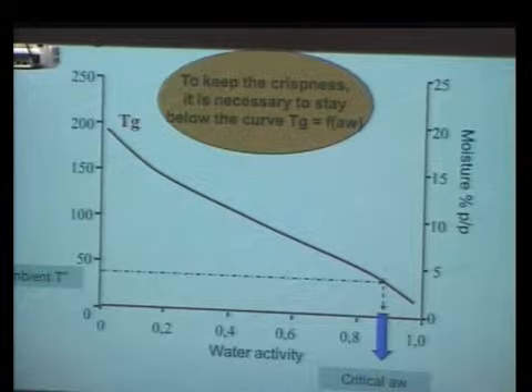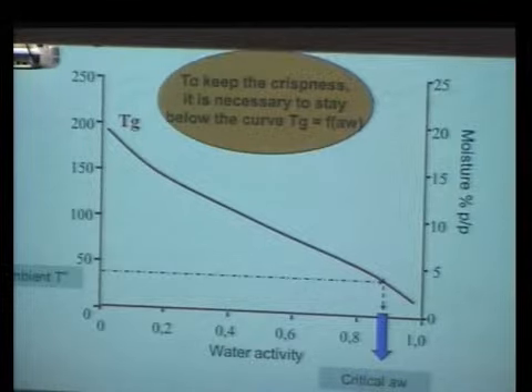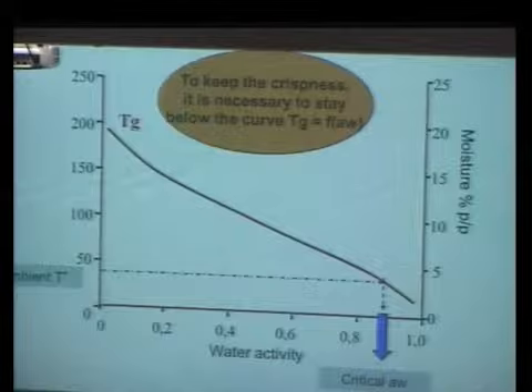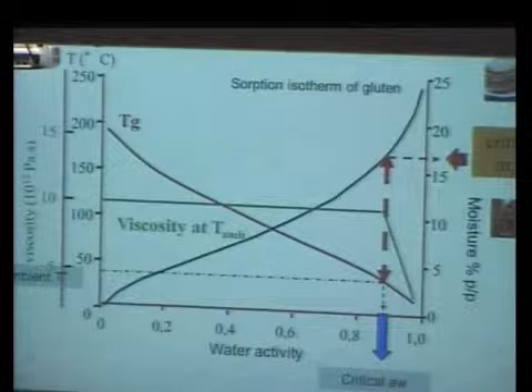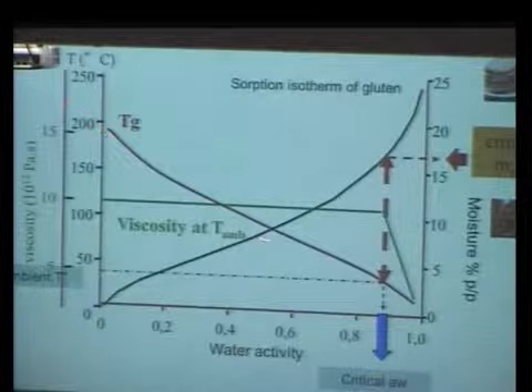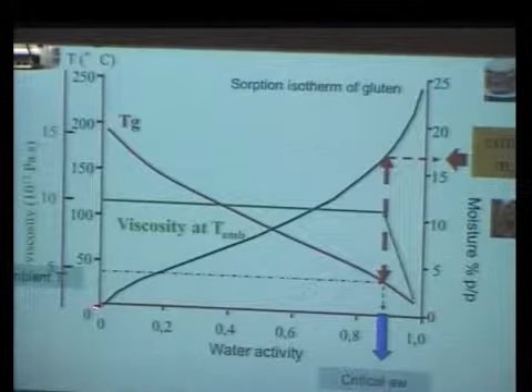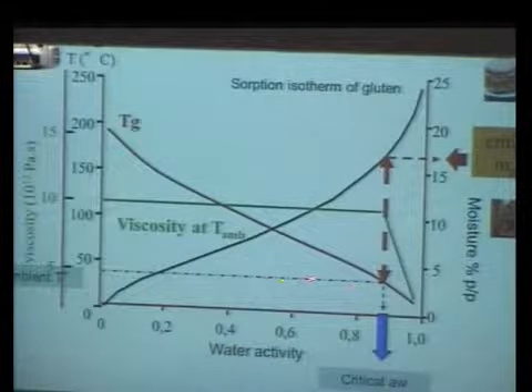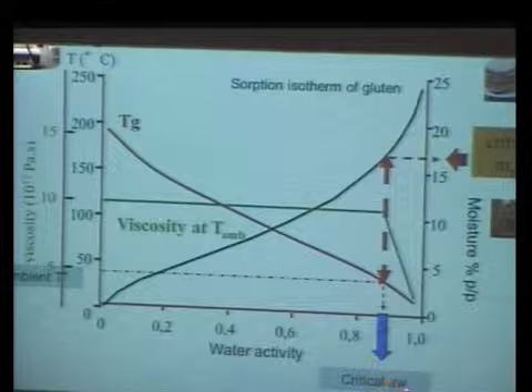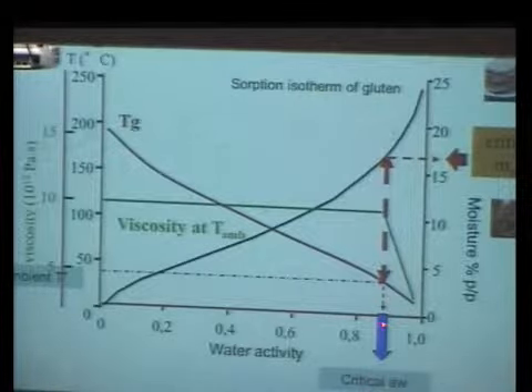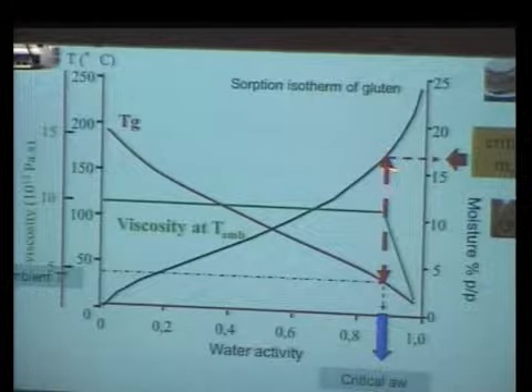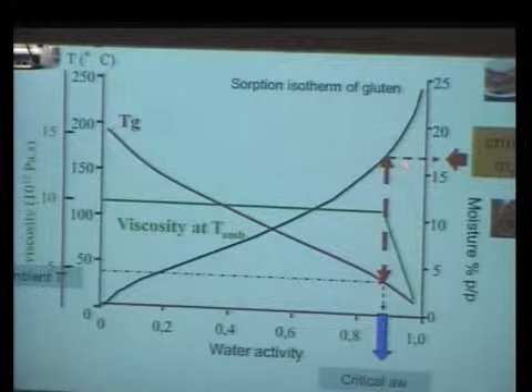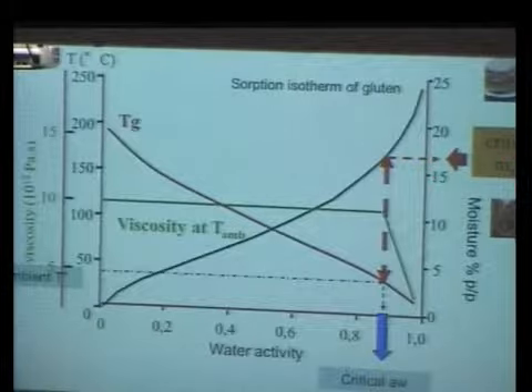But it's not very easy to have in your kitchen or in your industry something to measure water activity and so on. What you measure is, when you formulate a product, you consider the quantity of water you add. So you mix both curves, both tools: the glass transition curve here, and here the sorption. As we saw with these curves, we determine the critical water activity to keep the crispness, and when we report the water activity on the sorption isotherm, you can find the critical water content that should not be crossed.